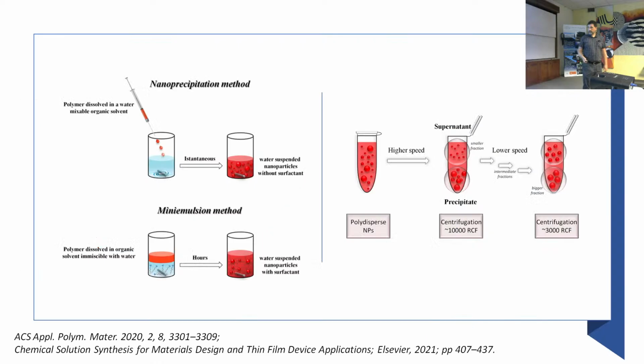So, the technique that we describe with some detail in this book chapter is the nanoprecipitation method. Here we have water, and you need to stir it. Then you have the polymer dissolved in a good solvent, like for instance THF, which is completely soluble in water. So, good solvent, bad solvent in here for the polymer. You start to inject the droplets, and with the stirring they are quickly dispersed within the water, and the polymer chains collapse.